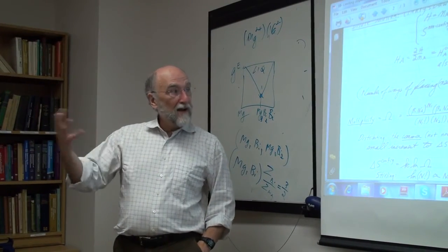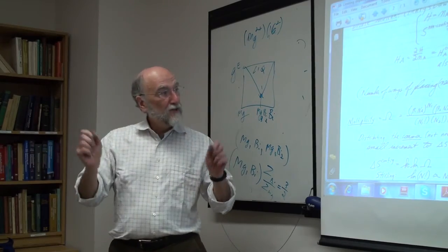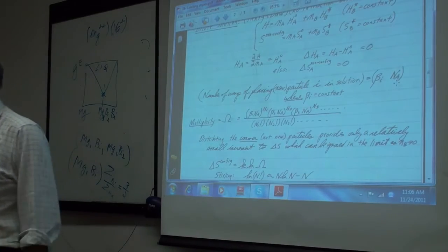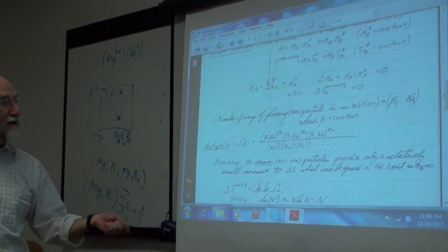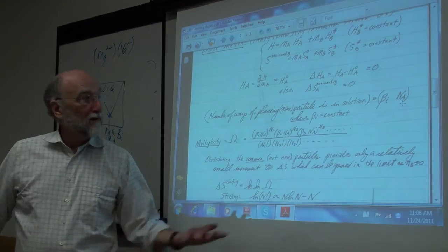In which you have 3 N_A sublattice sites, but the number of sites in which you can put your new particle is going to be N_A times some constant. Let's say I'm adding carbon to iron. Let's say I'm adding nickel to iron. The nickel goes in substitutionally, so β is going to be equal to 1. Every nickel ion can go in and is equal. The number of places to put a nickel ion is simply equal to the number of iron atoms that are there. If I put carbon into iron, and let's say you have 6 interstitial sites for every iron atom, then β is going to be 6. So the number of places where you can put your carbon atom is 6 times the number of iron atoms.